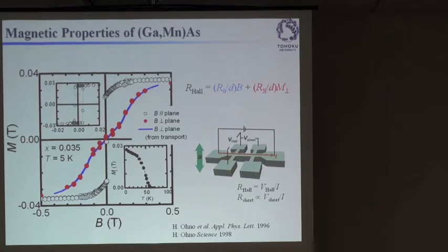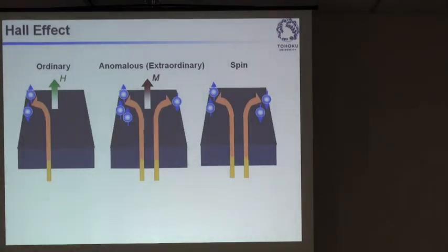And this is because the second term, the anomalous Hall term, is entirely dominating the Hall voltage in the temperature range that we are looking at, in the magnetic field range that we are looking at. So it's nice that we do not need to grow a rather large area material to do direct measurements. We only have to have a Hall bar to measure the magnetization of the material. Okay, this is just to explain what we are seeing.